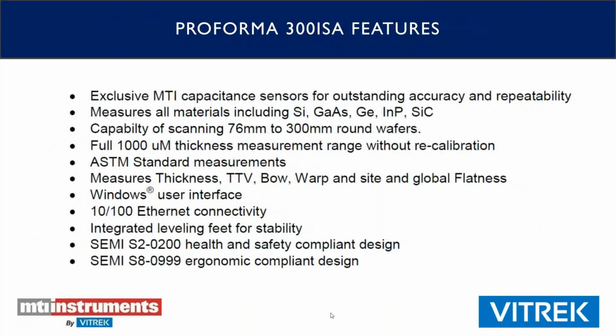Some of the other features, like again, it does use our push-pull capacitance technology. It does measure pretty much, I'm not going to say all, but pretty much all semiconducting and semi-insulating wafers. So it does include silicon carbide, obviously, silicon, gallium, indium, and other ones that are not listed here as well. So these do the standard wafers between 3 inches and 12 inches. It gives you a full 1,000 micron measurement range without recalibration.